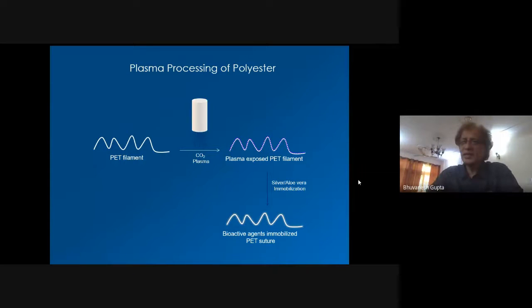So what happens in plasma processing? Like I give an example of polyester, which you people know very well. So what happens in plasma? You can treat it with plasma. So plasma ionized gas is falling on the surface of the fabric or filament. The energy of plasma is not much, hardly 8 to 10 electron volts. So it's not very high, but it's still high enough to break the bonds on the surface. It can break the bonds on the surface, but not in the bulk. So on the surface, you get the radicals, and these radicals can subsequently be combined with many other things, and you get the plasma processed material.